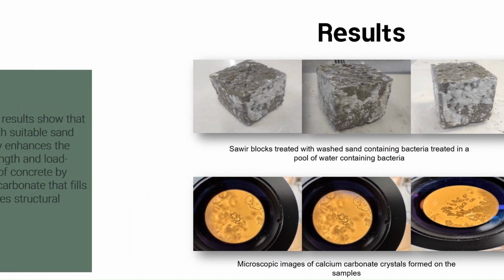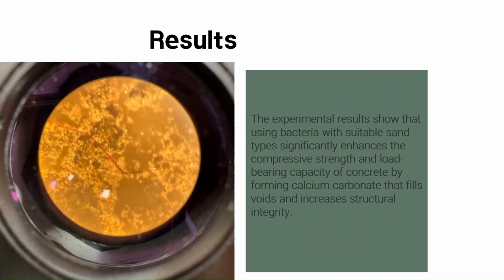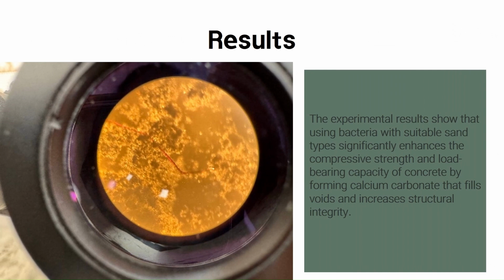The experimental results show that using bacteria with suitable sand type significantly enhances the compressive strength of concrete samples. The optimal condition in the ACS3 design highlights the potential of biologically enhanced concrete for improved load-bearing capacity. Bacteria play a beneficial role in forming calcium carbonates, which fill voids and increase structural integrity.